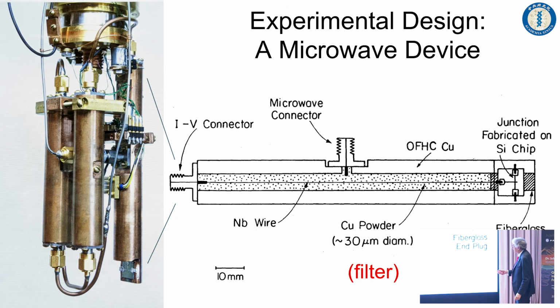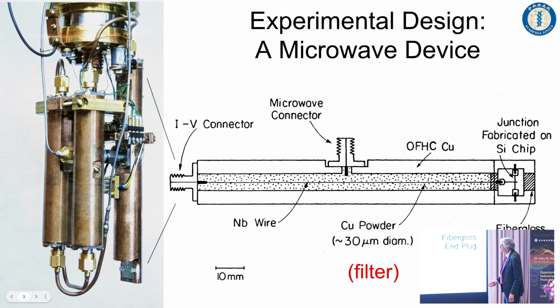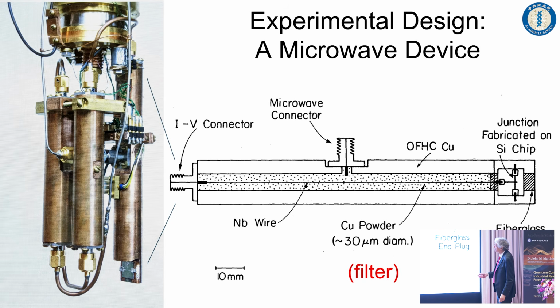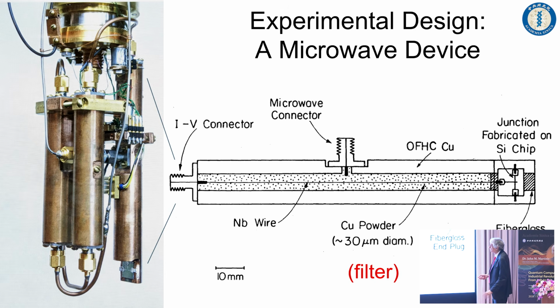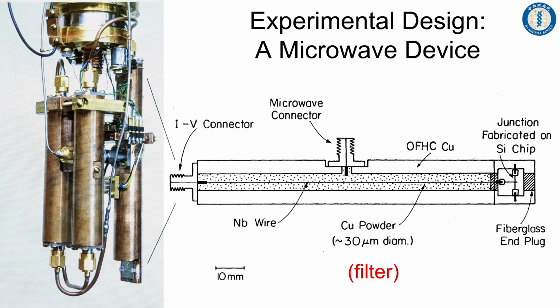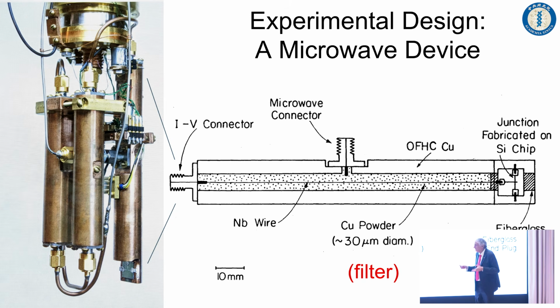Now, what you see here is the device down here. It's connected up to one filter and then goes down to a second filter, because we're really careful about doing everything. And then a secondary filter for radio frequency, about 100 megahertz to 500 megahertz or so. By doing that, we can make sure that the junction is really in a good quantum mechanical condition. Then we have a little connector right here, where we can put in microwaves, and that injects microwaves down into the line, and that excites the qubit chip in a way I'll describe in a few minutes. So this is the basic idea of what we're doing.